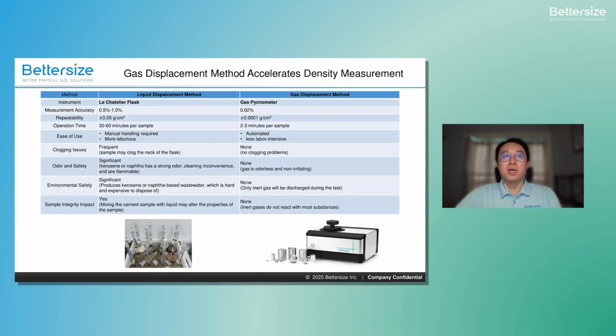In contrast, gas pycnometry, or the gas displacement method shown on the right, is a major leap forward. The measurement can be done automatically and incredibly fast, giving you highly accurate results in just 2 to 3 minutes. Critically, it is orders of magnitude more reliable. By using a safe, inert gas, it completely eliminates all the issues of the older method. There are no clogging problems, no odors, and no environmental waste. The choice is clear. For fast, precise, and safe density measurement, the gas displacement method is the modern standard.